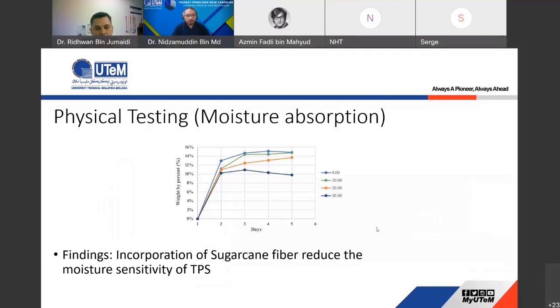One of the other problems with thermoplastic starch is that it is highly sensitive to moisture. It tends to absorb water, which affects the stability and the dimensional properties of the end product. We need to solve this problem, and by using fiber reinforcement, as you can see in this picture, the addition of fiber is able to reduce the absorption. Here, without fiber, the absorption is high, and when we introduce the fiber, it is able to reduce the moisture absorption.